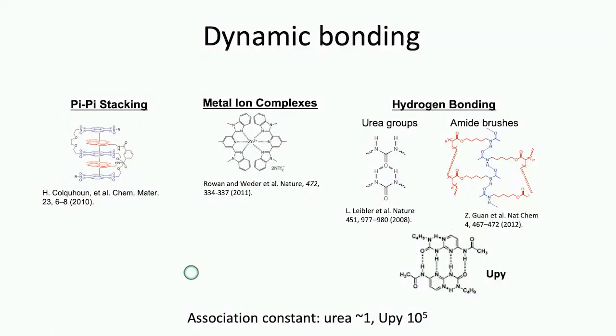Examples are chemical bonds that people have studied for a long time, in so-called supramolecular chemistry. There are various different types of bonds, and the hydrogen bond is a type that we have used quite extensively. And just to give you an idea of the type of tuning one can achieve with various types of bonds: for example, urea, this type of simple hydrogen bonding, has an association constant of 1, while if we use a design where 4 hydrogen bonds form simultaneously, called quadruple hydrogen bonding, then this will give an association constant of 10 to the 5th.